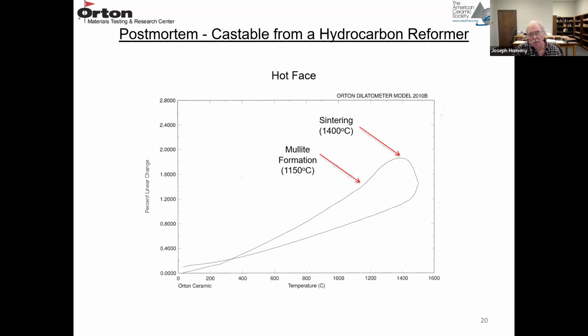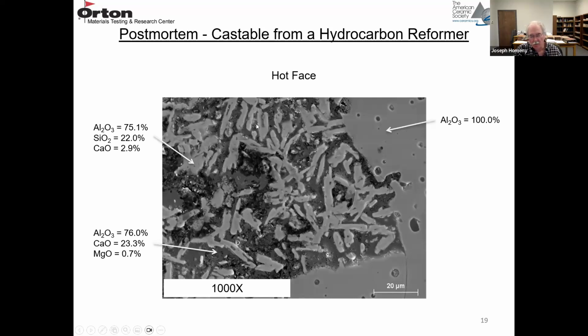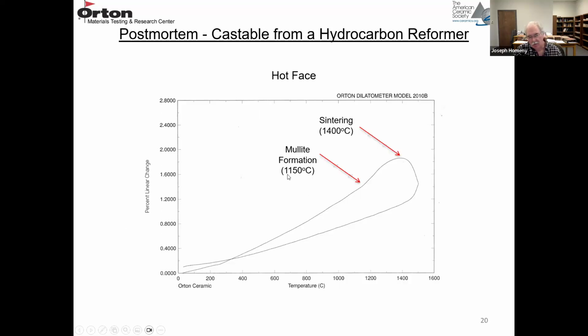So a castable is unfired before service. So reactions take place during service, and you can see them show up on a thermal expansion trace. So this top curve here is the heating curve, and then the bottom curve is the cool down curve. So we run a heating cooling cycle on this material to about 1500 degrees C. And the change in slope indicates a reaction taking place. So a little bit lower than 1200 degrees C, there's a slope change here. So that's where mullite forms. That's where these crystals are forming in the matrix. So I got temperature about 1150 where that slope change takes place.